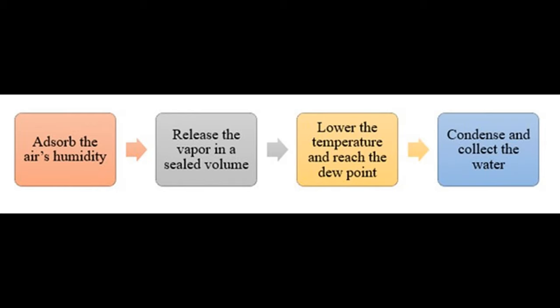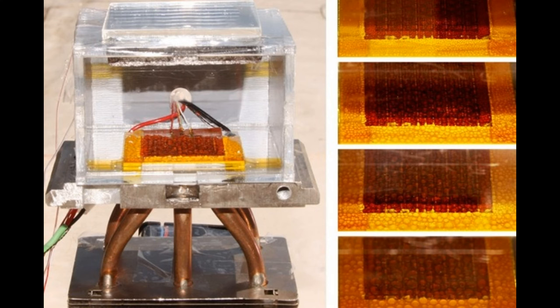Now let's look at some existing designs. A well-known design is one from MIT. The machine is very simple: a layer of metal-organic framework, or MOF, acts as a desiccant and absorbs water from the air, overcoming the problem of low water density in the atmosphere. After absorbing the vapor, the MOF is exposed to sunlight, which causes the release of vapor into the chamber. The lower surface, copper connected to a heat sink, is cooled down by the surroundings, allowing condensation of vapor on its surface.